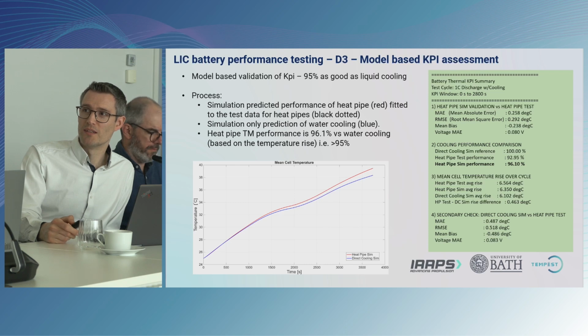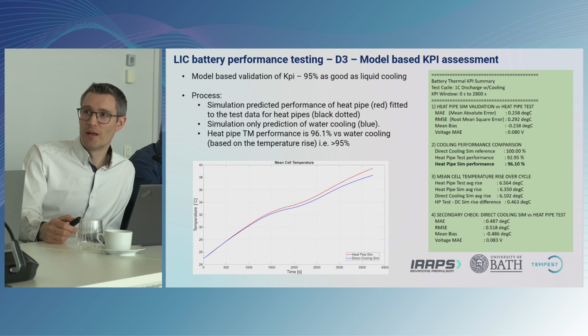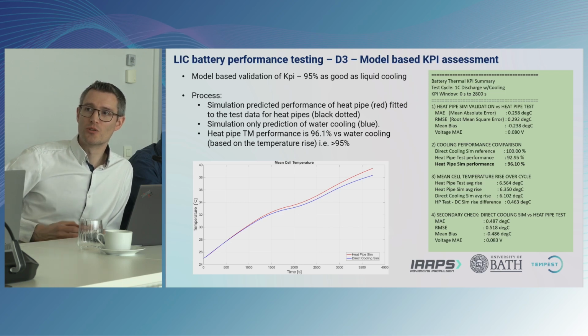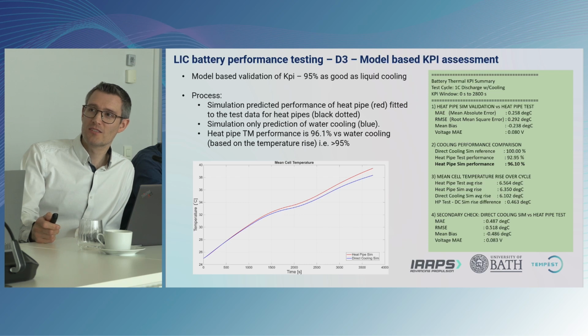The next most important thing is probably the second point there, looking at the cooling performance comparison. This was comparing the heat pipe cooled module versus the directly water cooled module. We were trying to evaluate whether we could achieve 95% as good a cooling with the heat pipe assembly as we could with direct water cooling. The results confirmed that: we had 96% as good cooling with the heat pipe assembly as we did with the direct water cooling. There was a KPI in the project based around this, and we were able to demonstrate that the heat pipe assembly system does achieve that performance.